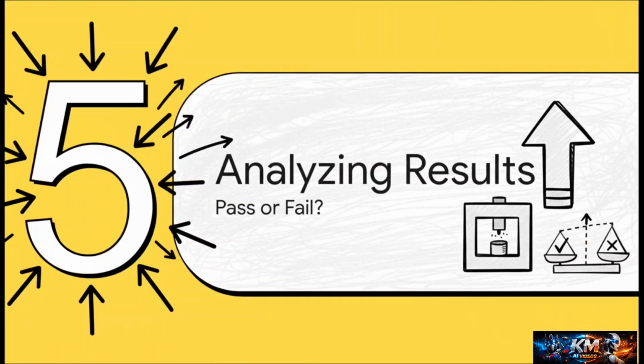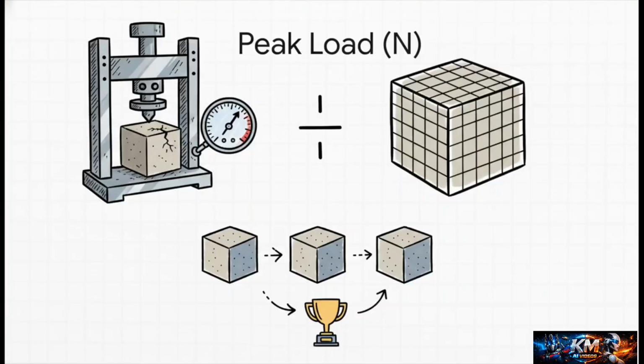Okay, the machine spits out a number, the peak load. But we're not done yet. That number is just raw data. Now, it's our job as engineers to turn that data into the final answer, the compressive strength. And the math is actually pretty straightforward. You just take that peak load the machine gave you and divide it by the area of the cube's face. And remember that weird 70.6 millimeter dimension? This is why it's important. It gives us that precise area to divide by. To be thorough, we always test 3 cubes from each batch and then average the results.